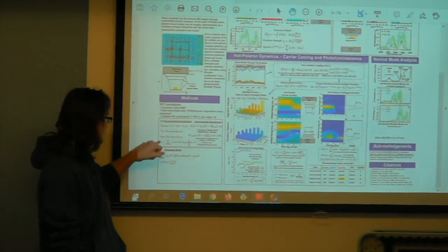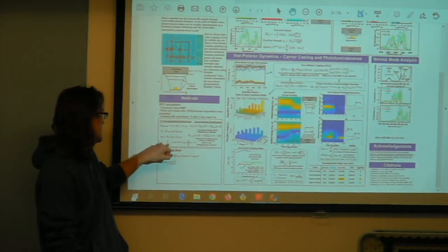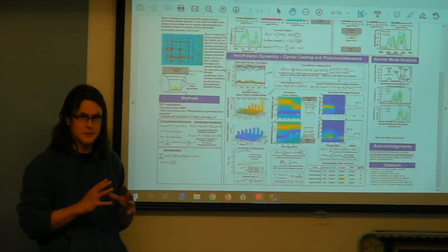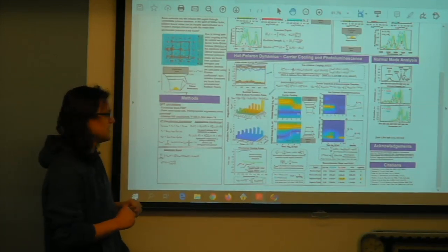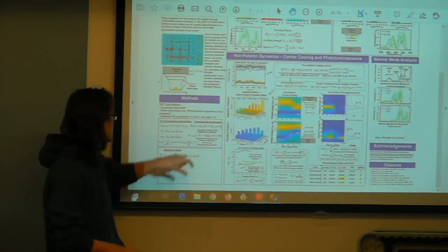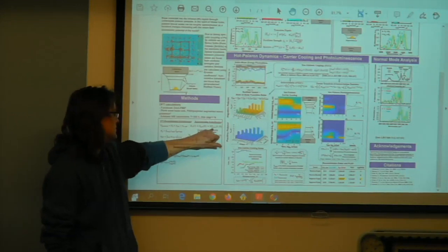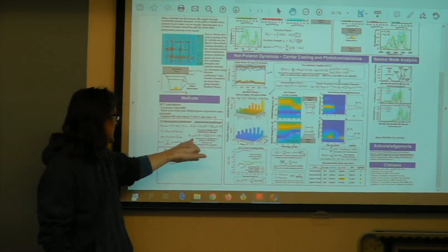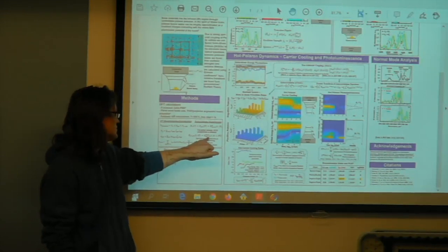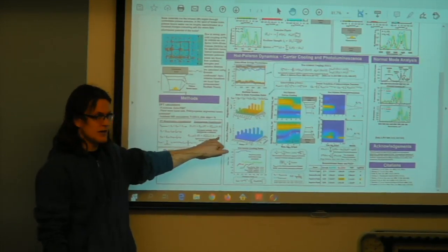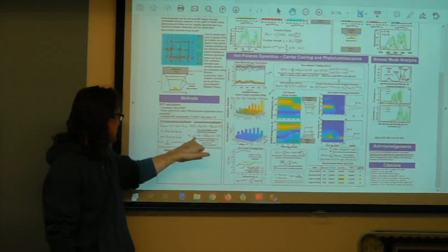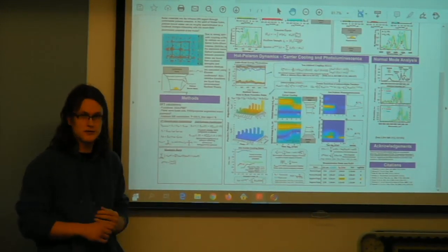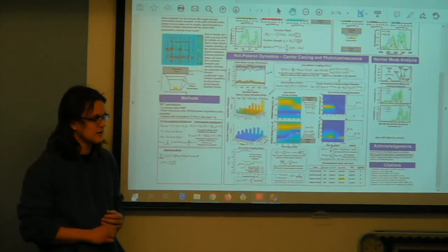The electron-phonon coupling, in some sense, describes the strength of the polaron formation. To approximate that in DFT, we compute an n-electron system as the ground state, then add or remove charges and let the model re-optimize. We approximate that as the electron-phonon coupling, so it's an approximation for the polaron binding energy.